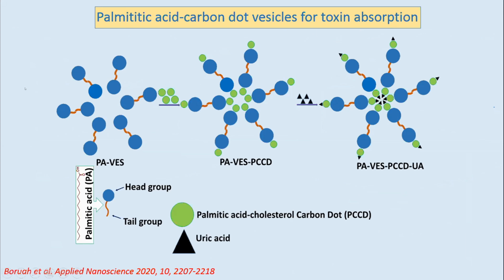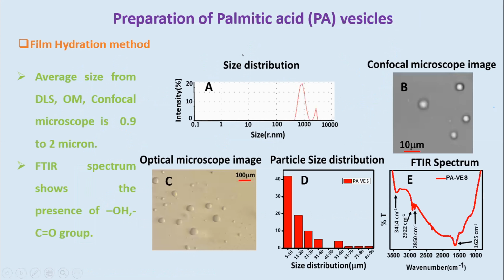So I attached these nanoparticles to the vesicles, similar to the earlier work. And finally, uric acid was used to be absorbed on the surface of the vesicles. It was observed that the nanocomposite system was very efficient at absorbing the uric acid available in the wash solution. So the characterization of the pure palmitic acid vesicles is here. You can see this is the spherical structure from an optical microscope image, and this is a confocal image.